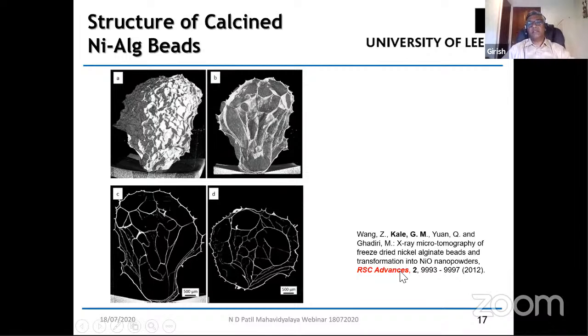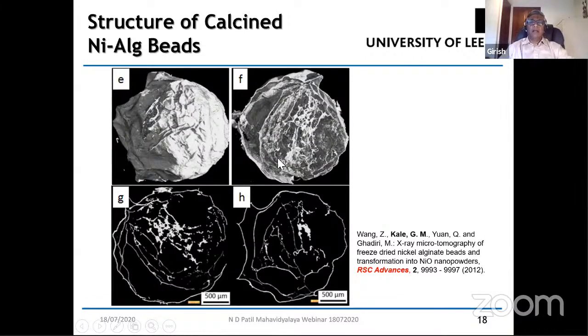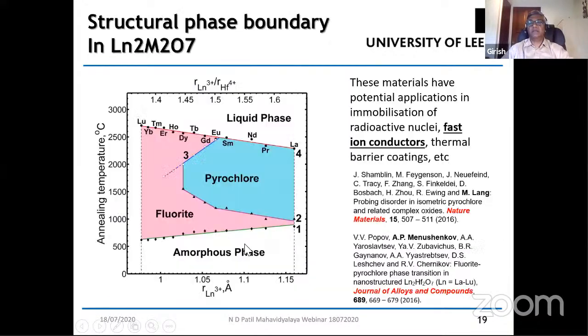This work was published in one of our papers in RSC Advances several years ago. In the same paper, we also published the calcined bead. So this was the dried beads, and you can see that even after calcination, the overall structure of the calcined beads is retained, and the empty spaces are still there, which prevents the particles from growing, but at the same time allows the particles to react together to convert into the product phase, which is a single phase product.